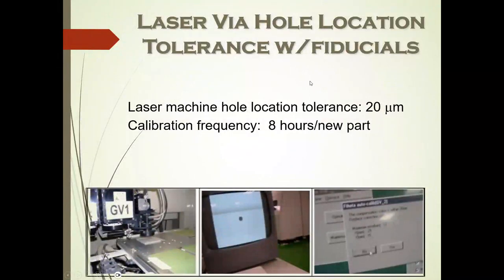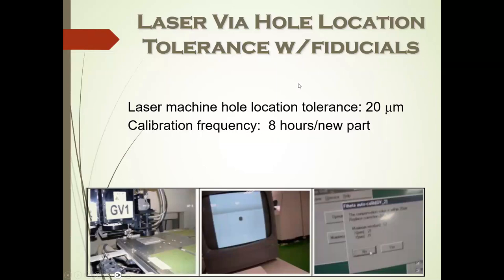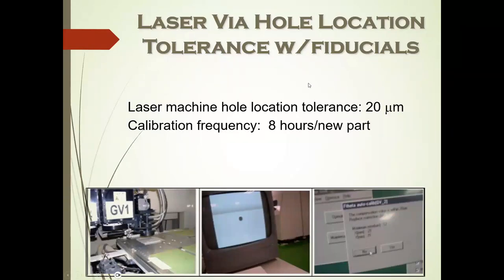One of the beauties of laser is that with optical, you can use and design the fiducials to get extremely tight tolerances — all the way down to zero annular rings, what we call a landless via. With the laser and the camera, it's possible to have a pad size that is the exact diameter of the finished laser-drilled hole. Consequently, strangely enough, it's more reliable than if you had a pad on it. That's covered in the Printed Circuit Handbook, chapter 60 on HDI reliability.